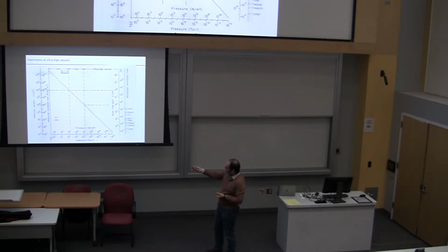If you are down here at 10 to the minus 12 torr, which is what I was saying MBE can get to, the graph shows that it's going to take months or years before something forms at the surface. Obviously this is very important for STM, where you want to look at the first surface. But for MBE, you don't want anything else to come into that chamber. So the main game is to get the chamber to the lowest pressure. To do that, you don't need water, so water has to go out. You have to bake the chamber. You want everything that goes in the chamber heated above 200 C so the water is out. There are no fingerprints inside the chamber, only the materials that you need.